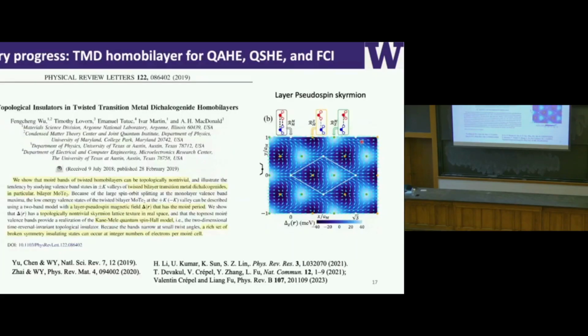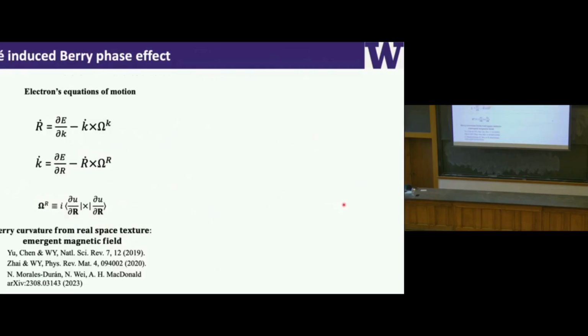Okay. The reason we studied this system is because Allan has this seminal paper showing that in twisted TMDs there's a flat Chern band. Then he shows that in the single particle picture, the system can be modeled as a quantum spin Hall insulator. Right? It's protected by time-reversal symmetry. What's really important, he shows that this layer pseudo spin actually forms skyrmions. Okay? And these skyrmions actually give rise to real space topology. And we can look into a bit more detail, right? Why these layer pseudo spin skyrmions give rise to this topology.